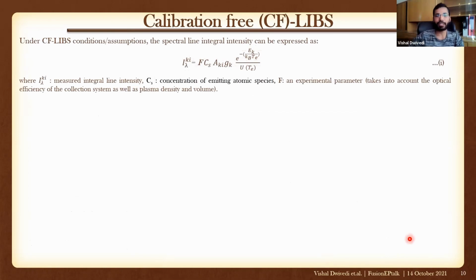So how can we calculate the composition using CF-LIBS? Under CF-LIBS conditions, the spectral line integral intensity can be expressed with this formula, where I is the measured integral line intensity, C is the concentration of the emitting atomic species, which we want to calculate, and F is the experimental parameter, and some Boltzmann factor and energy and temperature.